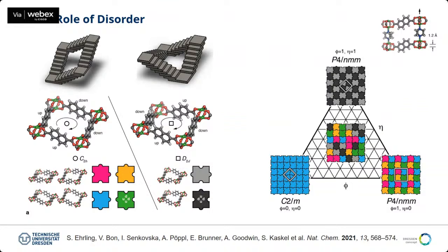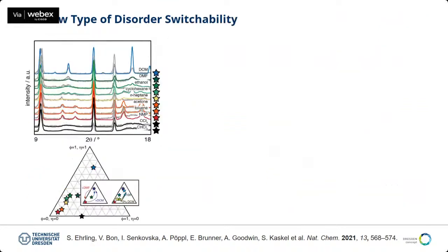So, which structure is the real structure of our MOF? We were quite suspicious, and we analyzed this very much in detail. What we found is that the guest, the molecule inside the pore of the structure, defines which kind of disorder we have. So you can have different kinds of tile combinations depending on whether you have a more polar solvent like DCM, for example, or a polar non-protic solvent like NMP, where you have more this kind of tile structure. We were very surprised that the solvent basically determines what kind of disordered structure is forming here.